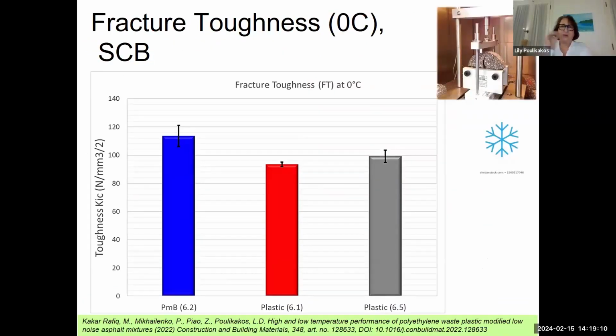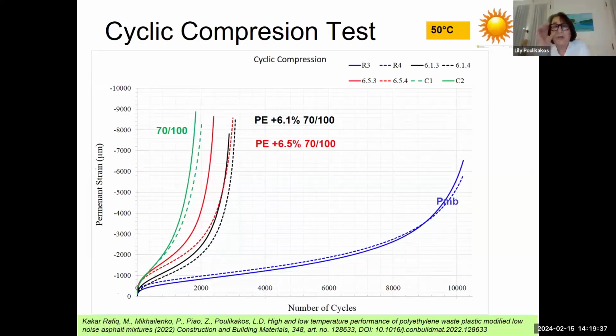So moving on now to cold temperature behavior, and now I'm moving on to the plastic modified mixtures. Now you see that using the semicircular bend test, our fracture toughness has decreased somewhat compared to our polymer modified mixture values. However, when we go up now to the high temperature range, we see that looking at the cyclic compression test here at 50 degrees, we have the number of cycles and the permanent strain. And we see that the two mixtures that include plastics could not meet the performance of the polymer modified mixture. So it did increase the performance from the straight run bitumen, but could not reach the PMB.